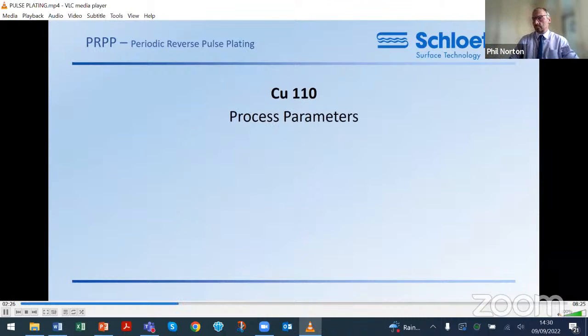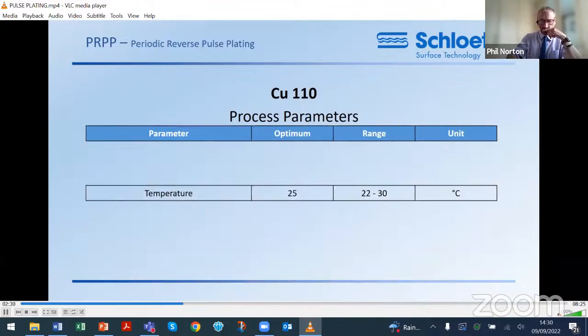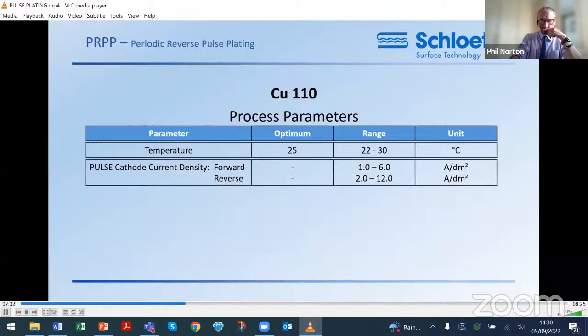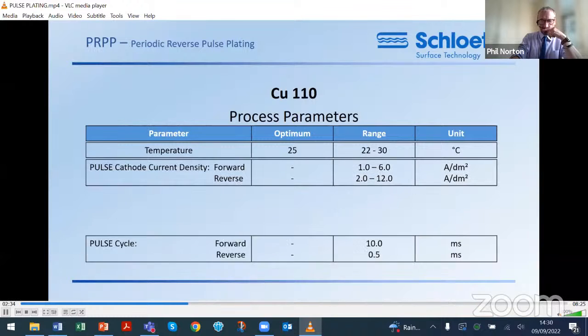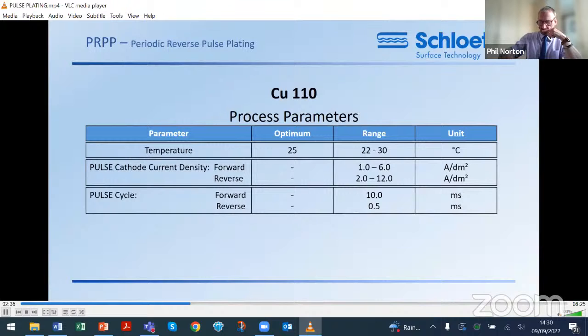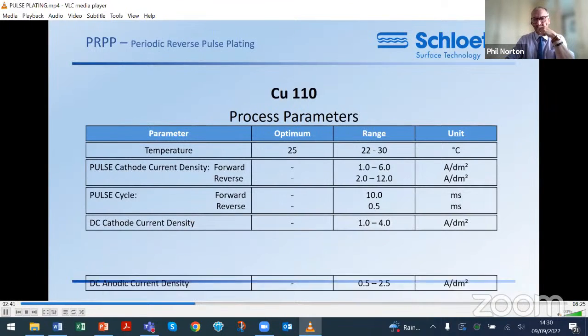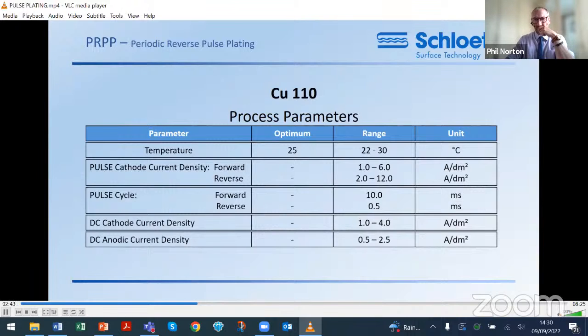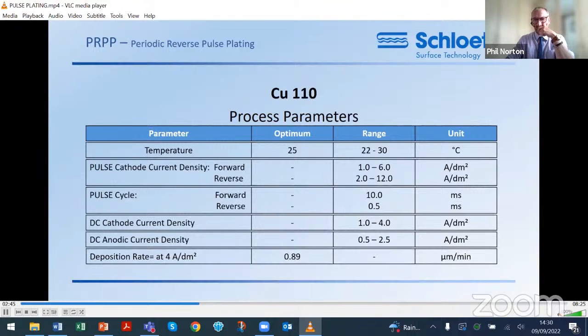Process parameters. The process is easy to maintain within wide parameters for temperature, pulse forward and reverse current density, and time cycles. These will be explained a little more in a moment, and DC, cathodic and anodic current densities. The process can be used in pulse or DC mode, and both modes can be incorporated into a plating cycle. Let's have a look how pulse actually works.